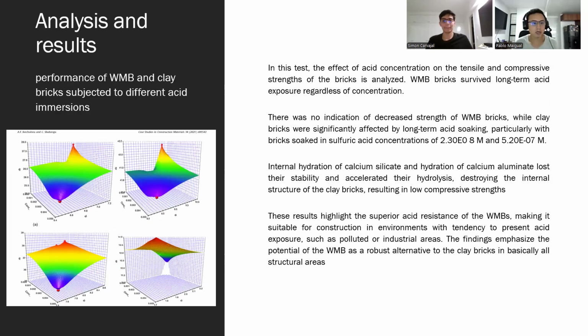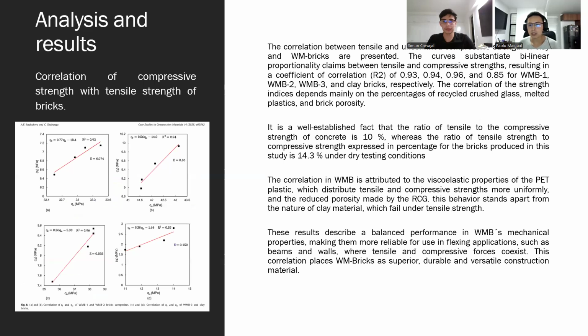Okay, and this is the performance of WMB and clay bricks subject to different acid immersions. The effect of acid concentration on the tensile and compressive strengths of the bricks is analyzed. Internal hydrated calcium silicate and hydrated calcium aluminate lose their stability and accelerate their hydrolysis, destroying the internal structure of the clay bricks, resulting in low compressive strength. The results highlight the superior acid resistance of the WMBs, making them suitable for construction in environments with tendencies to present acid exposure, such as pollutants in the industrial area.